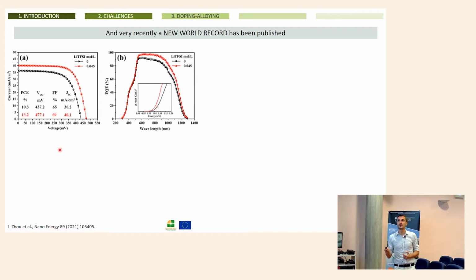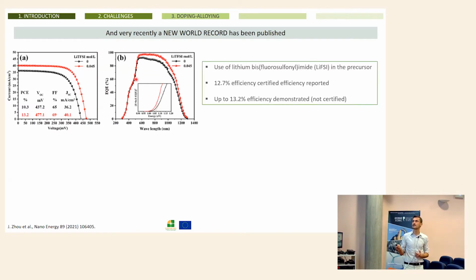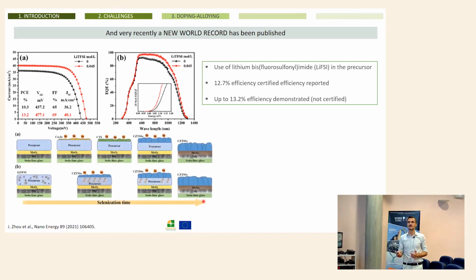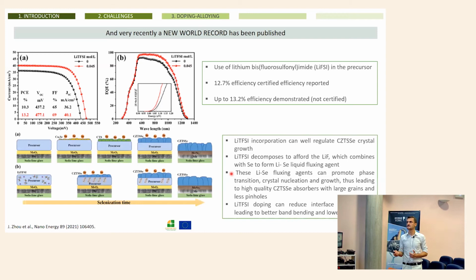Some months ago, basically, a Chinese group reported a new world record on kesterite working with lithium. They used lithium bis(fluorosulfonyl)imide in the precursor, and they demonstrated a very nice effect on kesterite. And then with this, they were able to produce a new world record with this material. In this paper, that is a very nice and interesting paper, they say that mainly lithium is acting as a crystallization flux, improving the crystalline quality of the material and having perfect grains on kesterite. And this is the reason for the improvement.